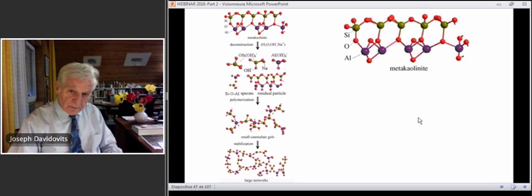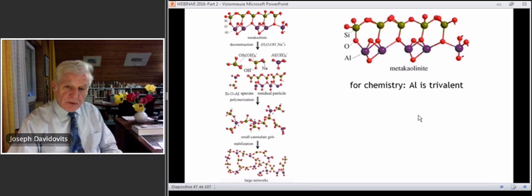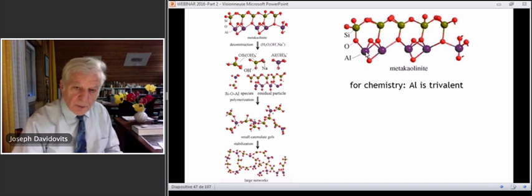What is the problem here? For chemistry, aluminum is trivalent. That is, an aluminum atom is covalently bonded to maximum 3 atoms of oxygen. So we have here silicium in green, in red the oxygen, and in purple the aluminum.